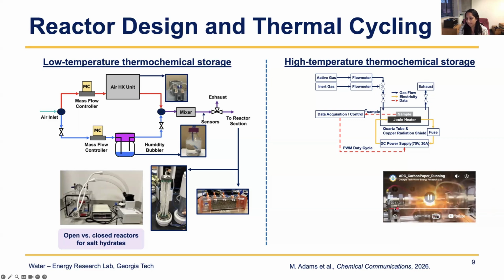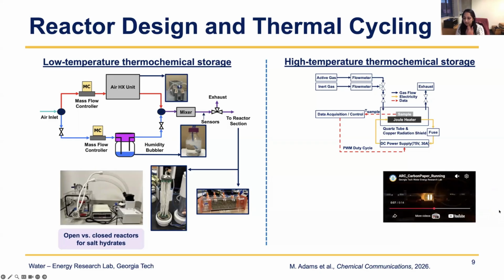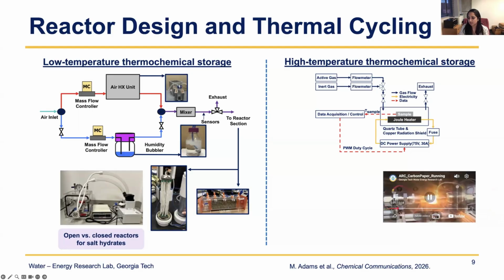And so here you can see the reactor that we've built to do rapid cycling. And we use direct joule heating. So give current directly to a porous carbon heating element, and the porous carbon heating element heats up, goes up in temperature. So you can see it's glowing here because it can go up to about 1,200 degrees Celsius and very rapidly come back down and repeat this thousands of times. So it's all within a quartz tube to hold everything and seal it from the external environment. And we have this PID control that we've developed to give us very rapid heating and cooling rates.